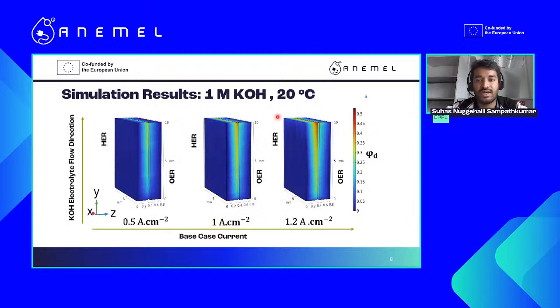Current density also has an effect. We have to apply external power to split the water. So this translates directly to current density, which results in the voltage characteristics of the cell. So we have control over the applied current density. When we apply a certain current density, it also has an effect on gas fractions. And this is a cool study because the current density is controlled by the electrochemistries as well as the evolving gases CFD that is involved.